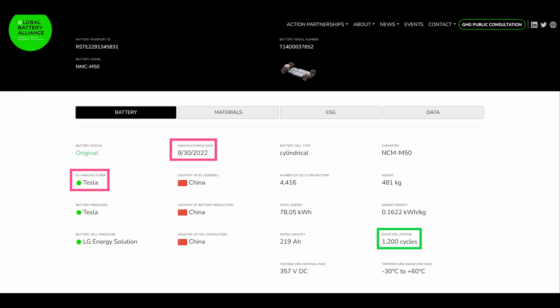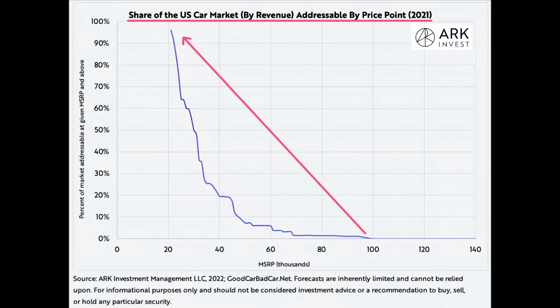That's because currently, 5 years on from the million-mile battery paper, commercially available nickel-based lithium-ion batteries are usually achieving at least 1,200 cycles. On a vehicle with 300 miles of range, which is now common, after factoring in capacity loss, that's roughly 300,000 miles over the life of the vehicle, which is more than enough for most vehicle buyers. That makes higher cycle life low priority. That's as opposed to cost, which is almost always one of the top priorities for vehicle buyers.